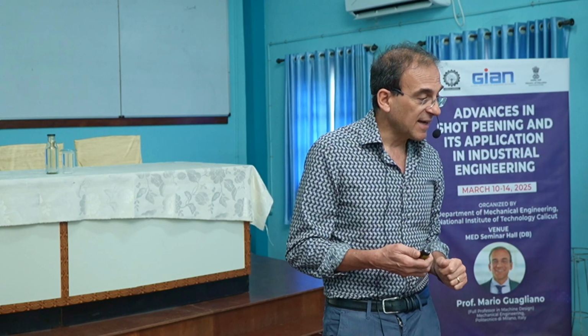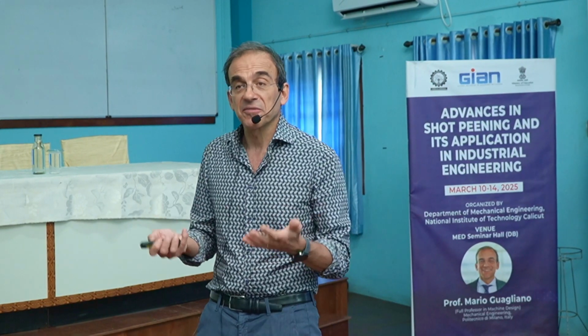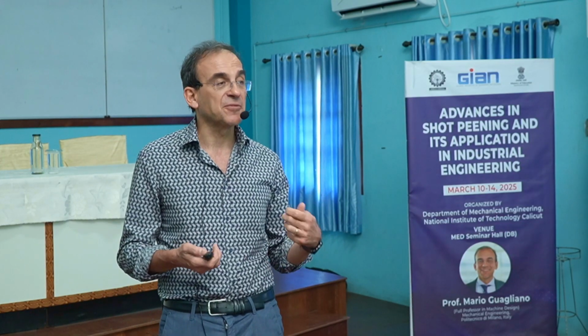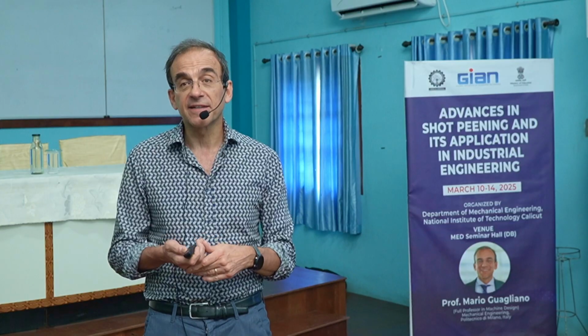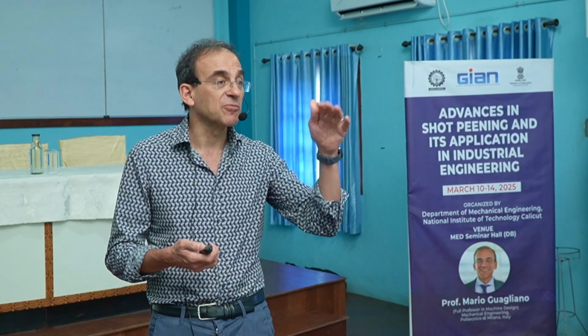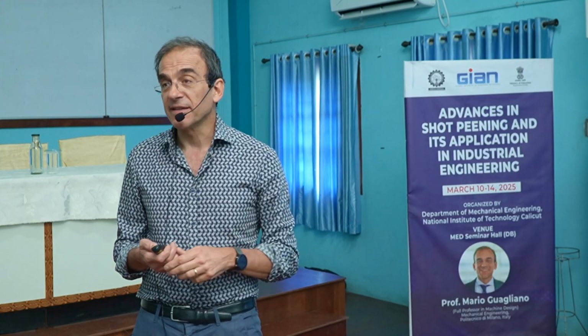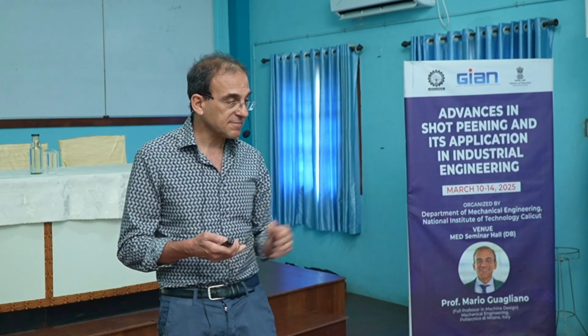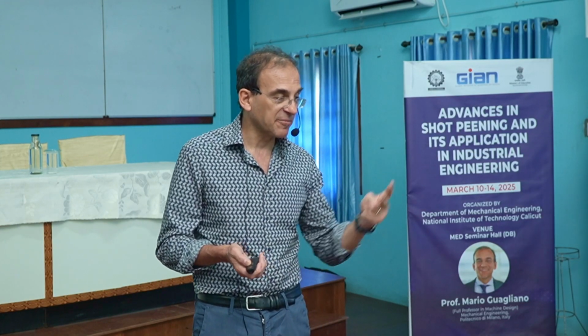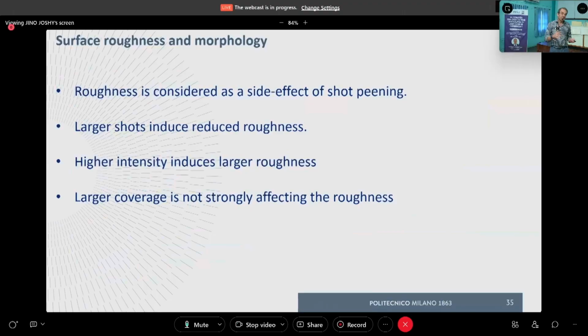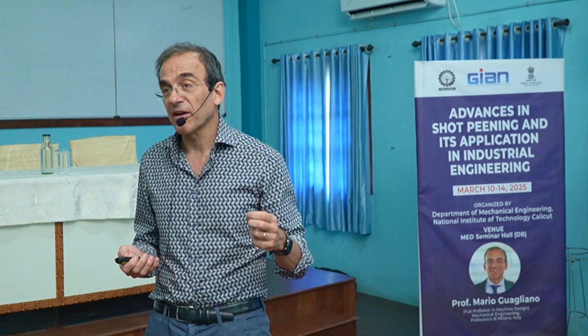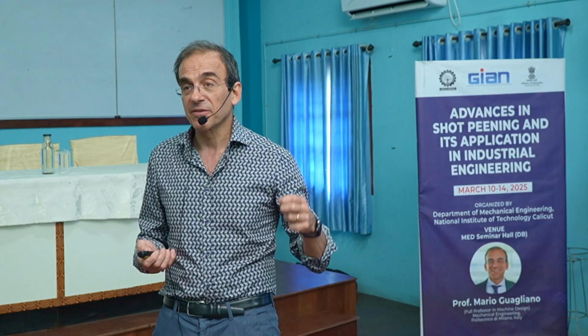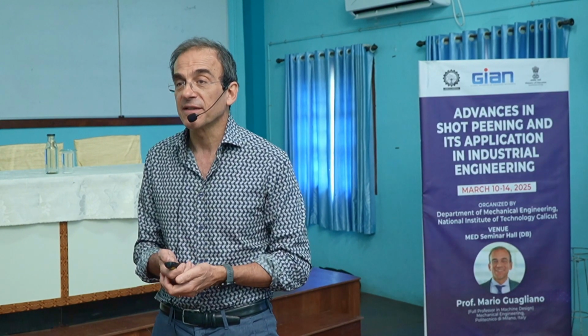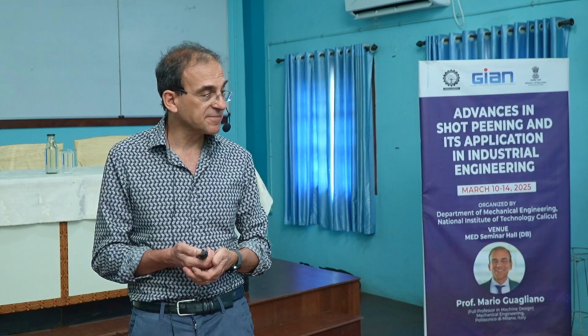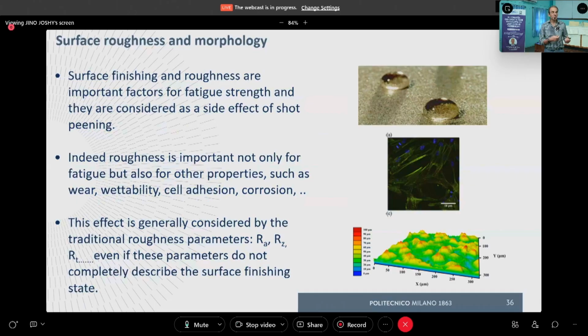The second is that higher intensity induces larger roughness. Also, this is intuitive. If we are increasing the intensity, it means that we are increasing the velocity and finally the kinetic energy of the impact. And this will make the indentation deeper and will increase the roughness itself. If we talk about coverage, the other parameter, coverage can have an effect, but the effect is finally a bit asymptotic. So the effect of coverage on roughness is not as important as the effect of the shots and the effect of the intensity. Okay, but let me now show you some other cases.